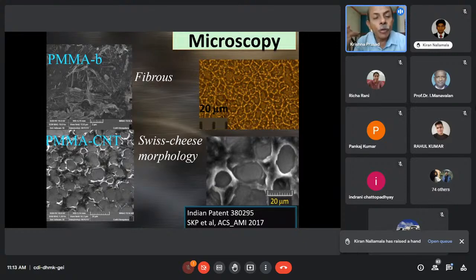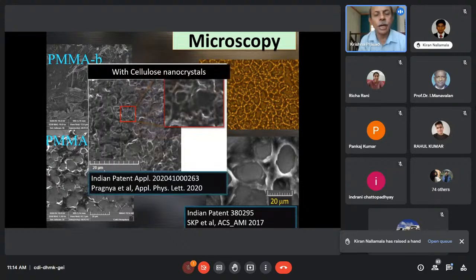So we could now get rigid systems, even though the polymer content was comparable to the typical PSLC system. So the CNTs were truly reinforcing the polymer network, and therefore we were ending up with a droplet morphology. And we got several interesting results, and we also filed a patent which has now been granted. And Marlene Barral, who was working on this, was pretty happy with the kind of results that we got here.